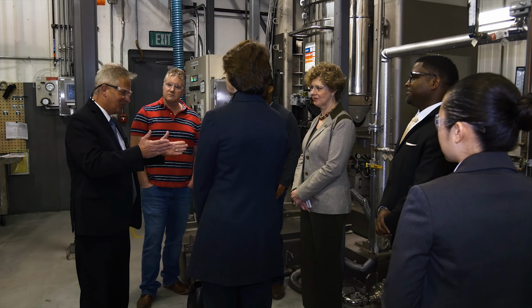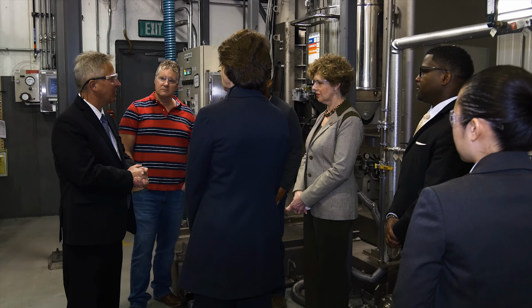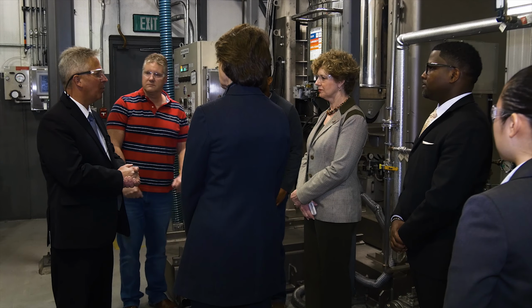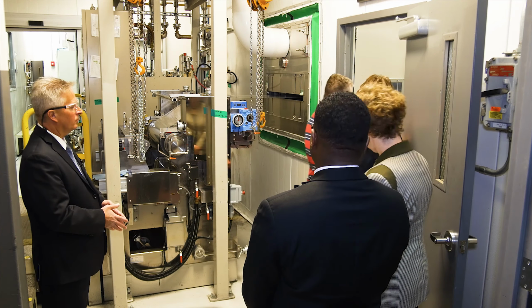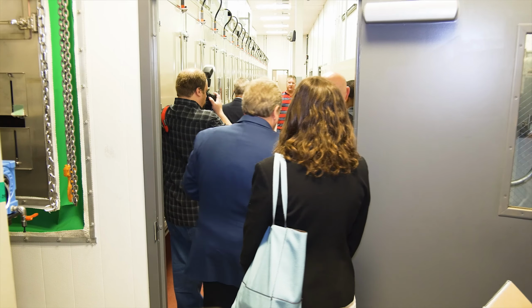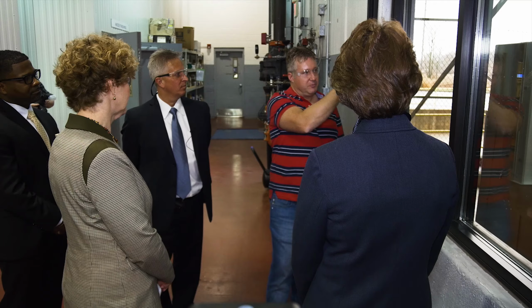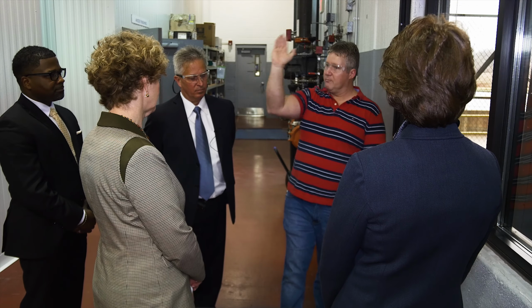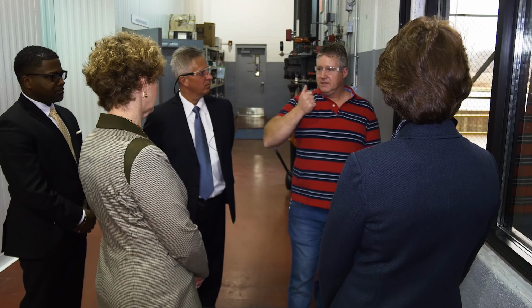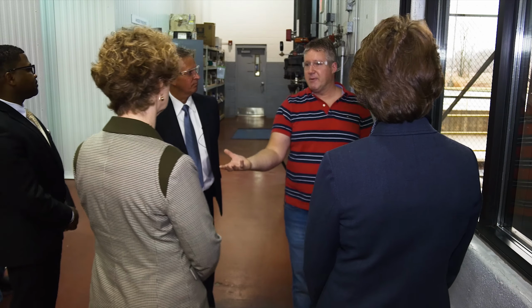Many have tried, including us, to take that 14 days down and reduce it, but there's not been anything as reliable. So we continue to use that process. And that's really a global standard with most all manufacturers in this business. We use NMP throughout the entire process, probably from this wall back, because that cleans up our coater heads. We use it in our actual material slurries, and we use it for all of our cleanup in the mixing rooms as well. So anytime you mix a slurry, you got to go back and clean it out with a solvent.